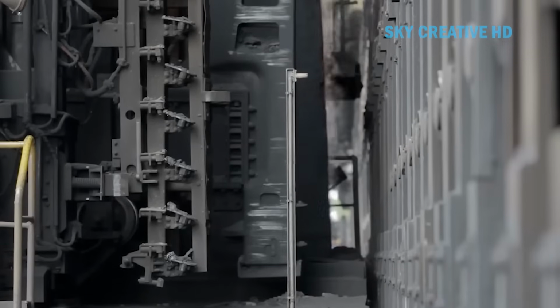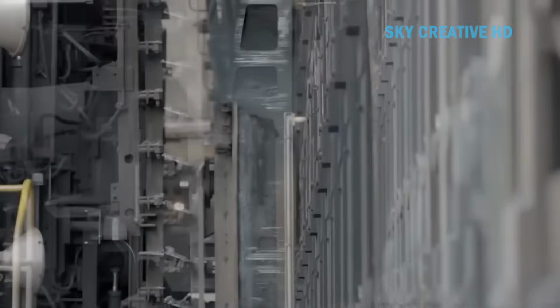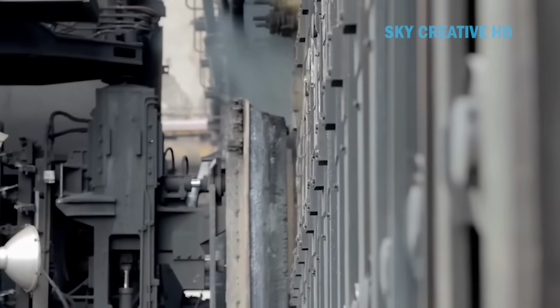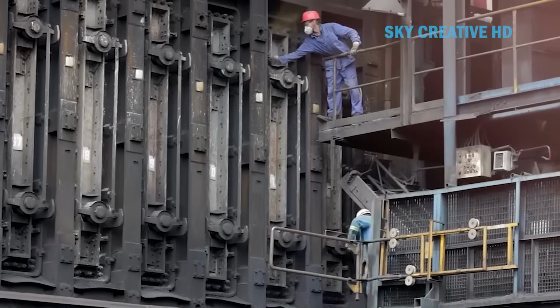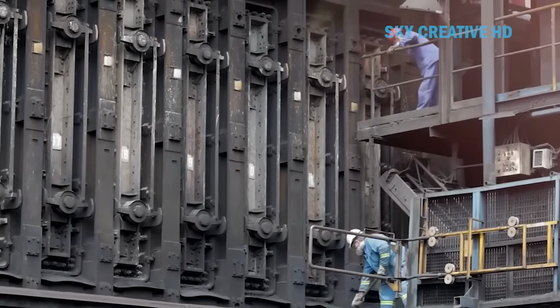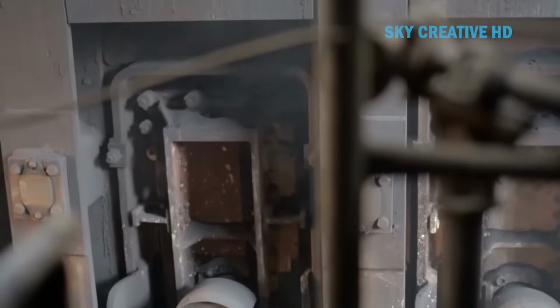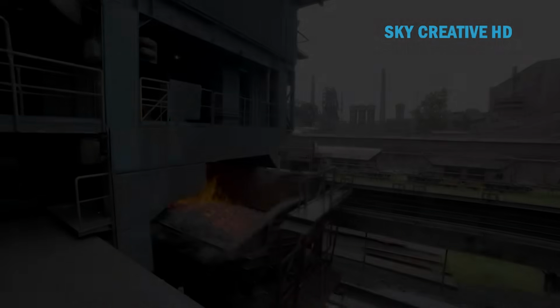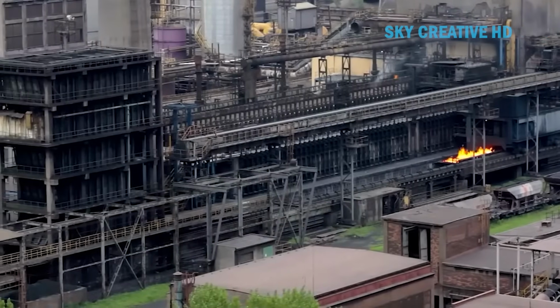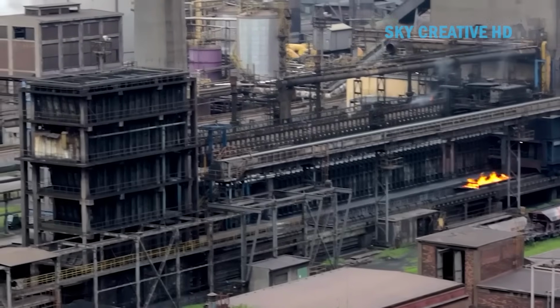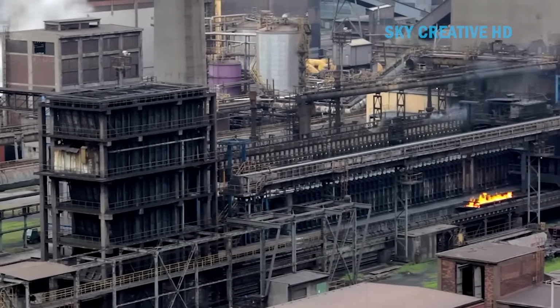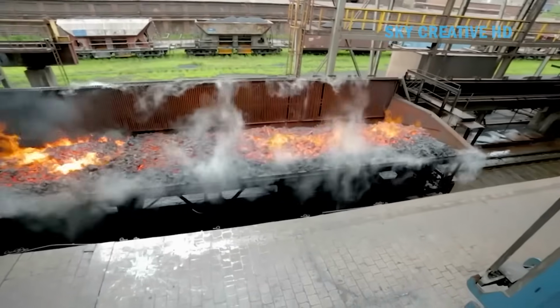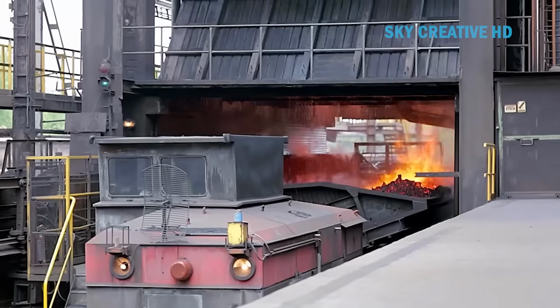And watch as these materials feed into the blast furnace, a towering structure that's essentially a controlled volcano reaching temperatures of 3,000 degrees Fahrenheit. Hot air, preheated to over 2,000 degrees, is blasted into the base of the furnace, creating a chemical reaction that separates pure iron from the ore. What emerges is molten iron so hot it glows white, flowing like water into massive ladles. But this is only pig iron, useful, but not yet steel.